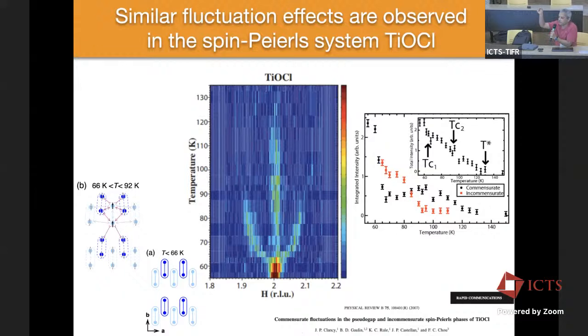So, as you mentioned, you expect more of a streak rather than the Bragg spots. So the first question was that you don't see anything at 94 Kelvin, right? Any discontinuous change in intensity? Yeah, so we don't see anything special at 94 Kelvin, except in the measurement of the lattice parameter, right?